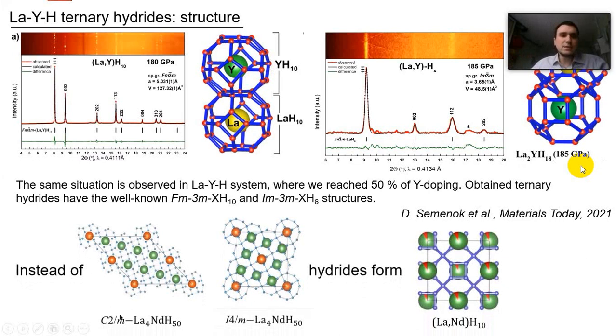Okay, and it's interesting to note that for other hydrides, the situation is similar. For instance, for lanthanum neodymium hydrides, lanthanum and neodymium also do not occupy certain positions. They are mixed, and actually it can be described as a solid solution of lanthanum and neodymium in the metal sublattice.